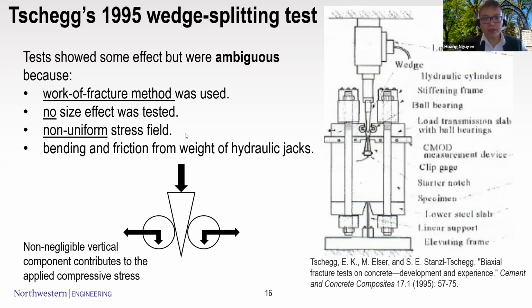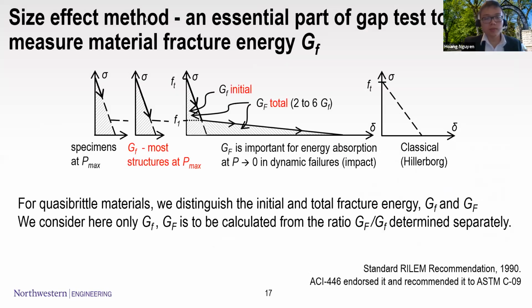However, one big caveat of this test is that you have a non-uniform stress field, or non-uniform crack-parallel stress field, because when you apply the opening mode here, a certain part of the applied load goes into the vertical component, and that vertical component transfers into the specimen, and then you have non-uniformity in the stress field. So one key point of the gap test is the design and how to apply the crack-parallel stress onto the specimen. Another is the size effect method.